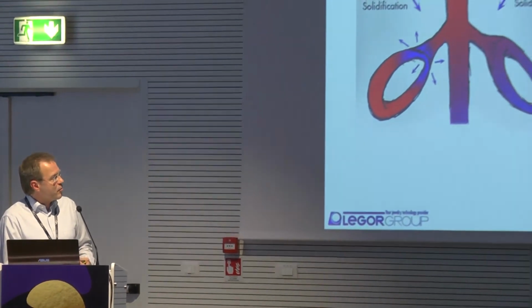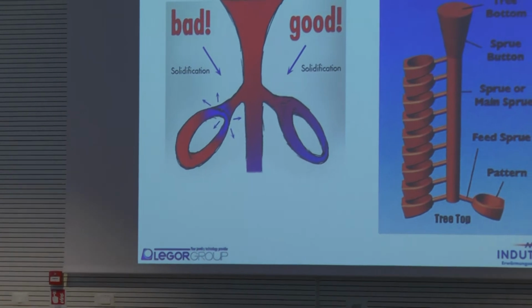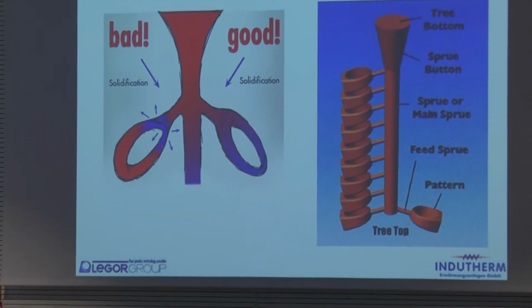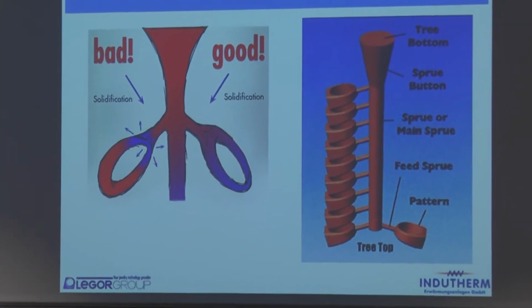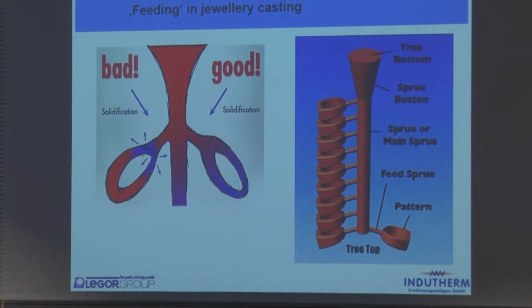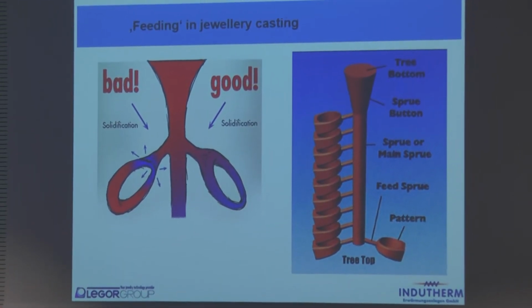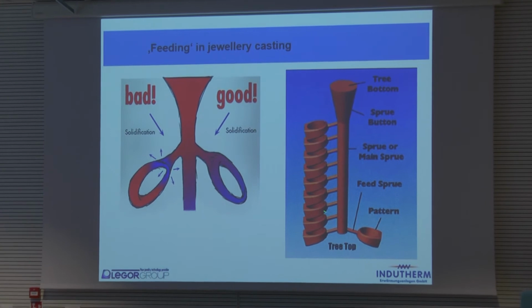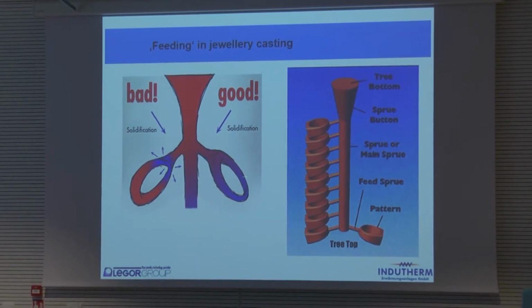In our jewelry casting, how does this work? We have a main sprue and we have gates or feed sprues. And yes, the task of these parts of the casting is to supply the molten metal during the filling process. And the second task is to feed the solidifying part during the solidification process in order to avoid or minimize shrinkage porosity. So the way of sprueing is very important.